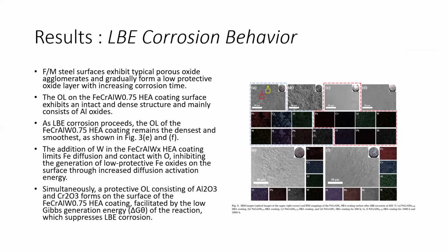So we talk about LBE corrosion behavior. F/M steels exhibit typical porous oxide accumulation and gradually form a low-protective oxide layer with increased corrosion time. You can see the ferrochromium aluminum tungsten 0.75 coating exhibits a dense and thin structure, mainly consisting of aluminum oxide. As LBE corrosion proceeds, the sample coating retains the dense structure shown in figure 3(e) and (f).